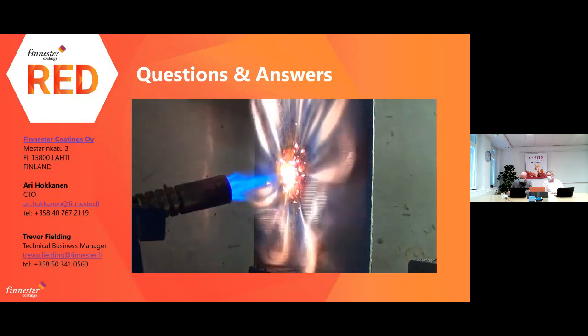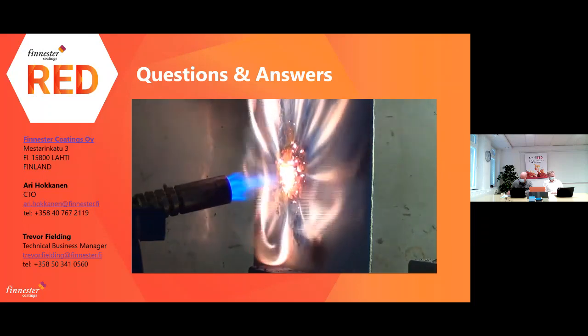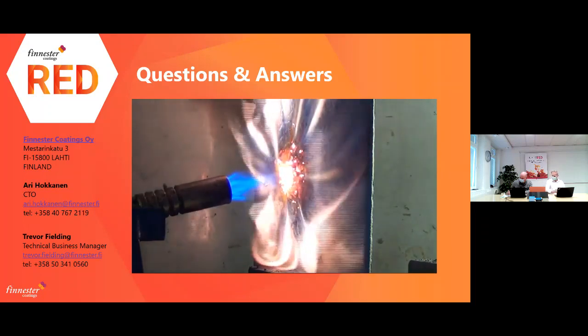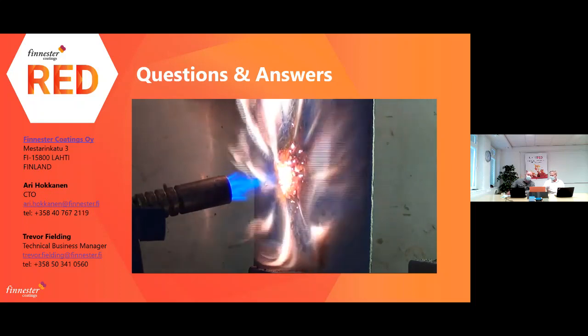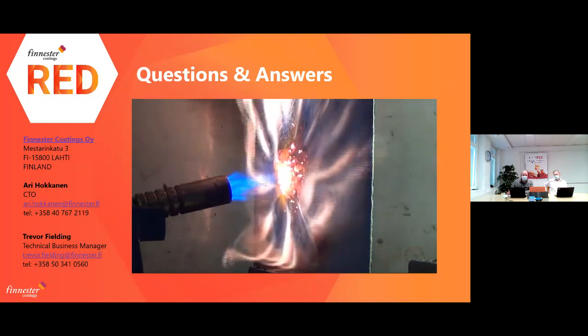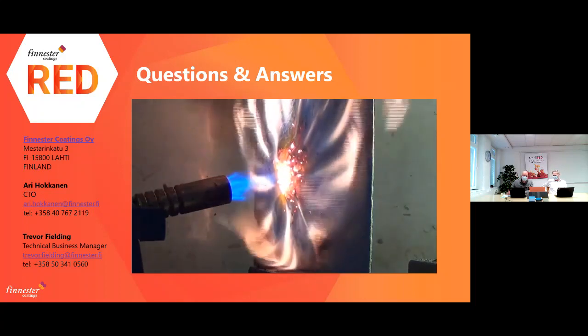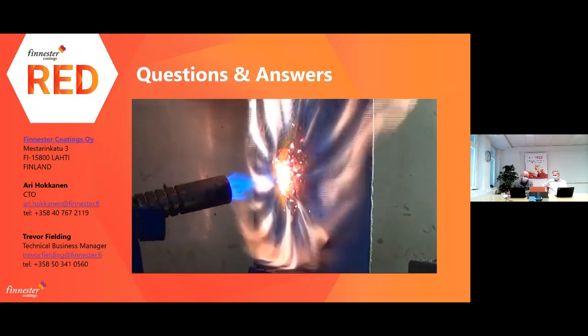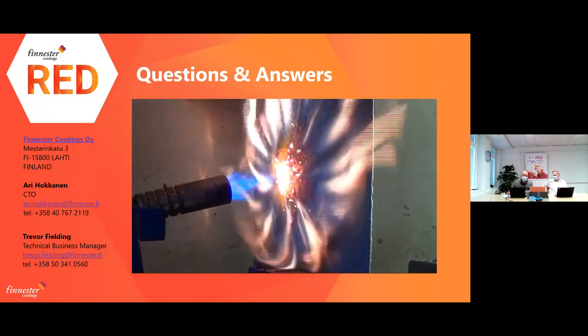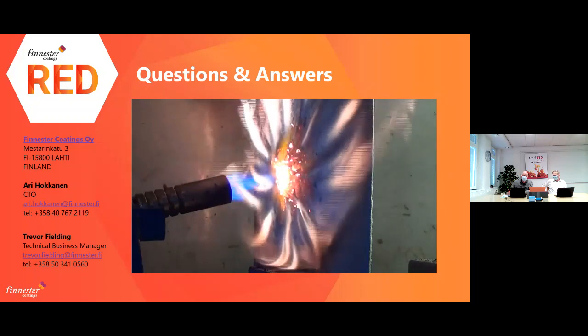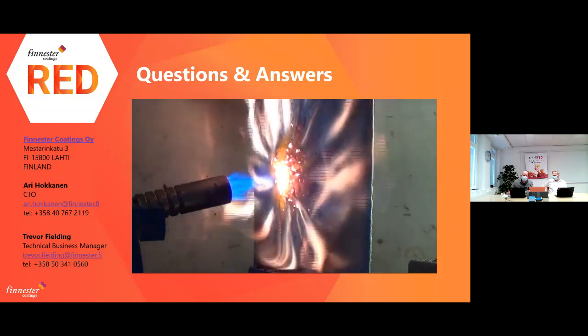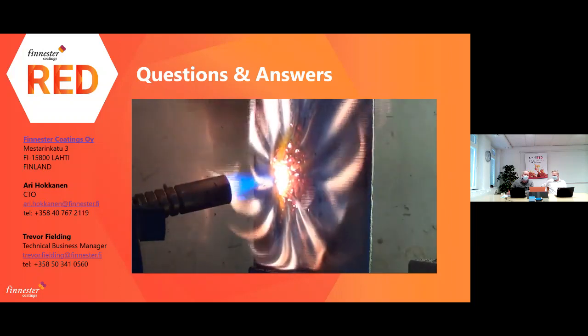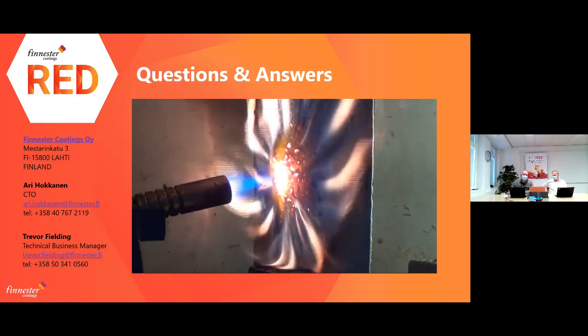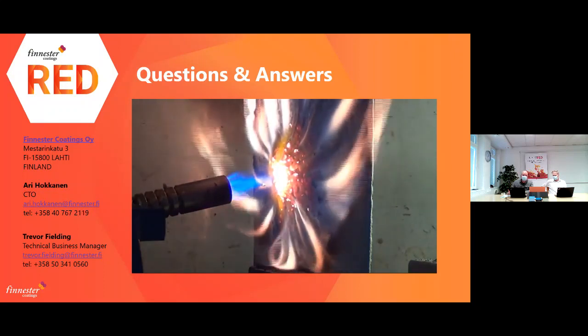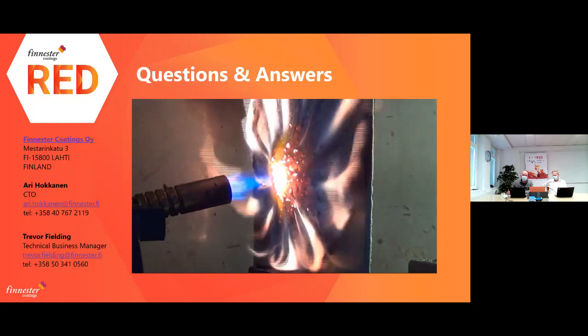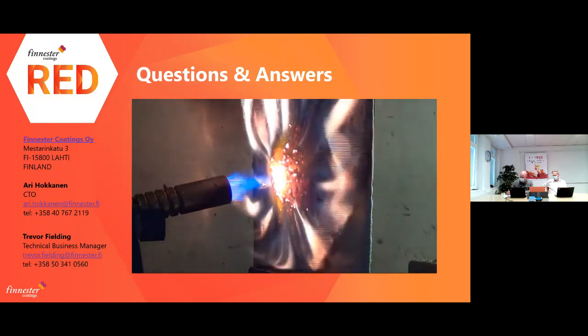And we have a question of, can it be used as a gel coat? Good question. Pure Red, the primary intumescent primer, can be used as a gel coat. The hybrid Red, the top coat, cannot be used as a gel coat. It's a coating, so after demolding the part, you can paint it like your car or your furniture. So pure Red as a gel coat, hybrid Red not, it's a coat.